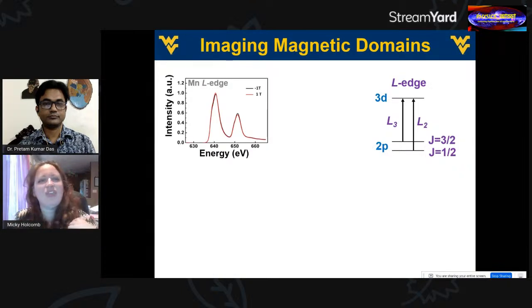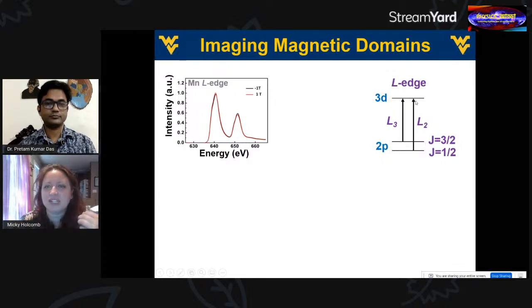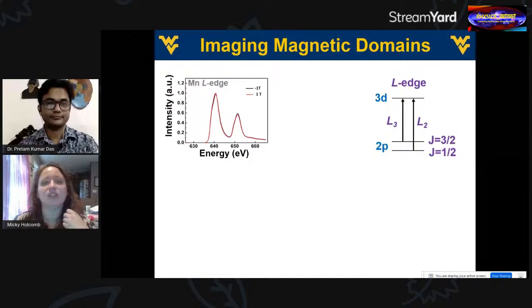The cool thing about that is that you can even image your magnetic domains. So for example, here I'm looking at the manganese L edge. You'll notice that in the 2p level, of course, we have two different levels, so two different energy levels that can be excited here. They have different names, so that's what these two different peaks are. And if you look very closely, you'll notice that there's a very, very small difference in the absorption of these peaks, depending on which direction my magnetic field is applied, and that's relative to the magnetization within the sample.